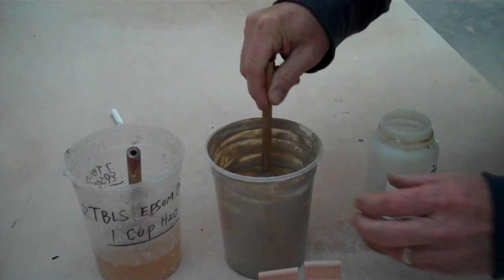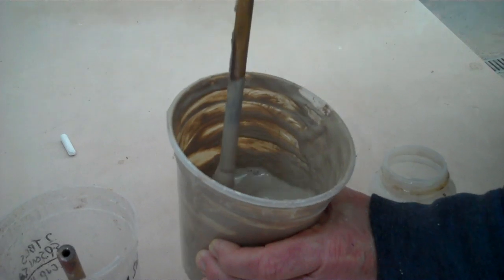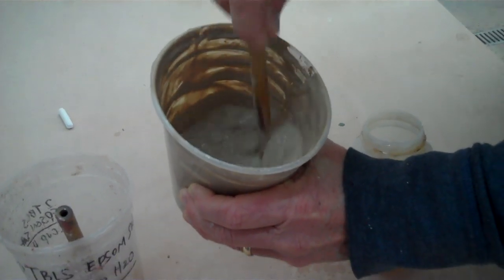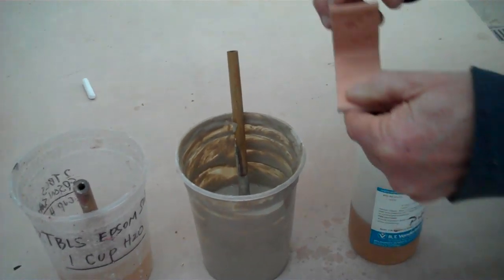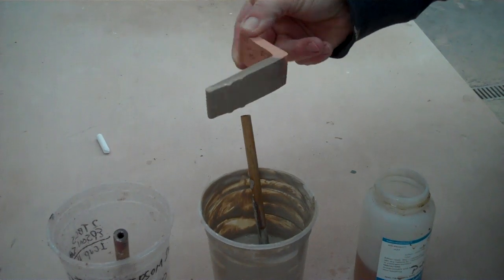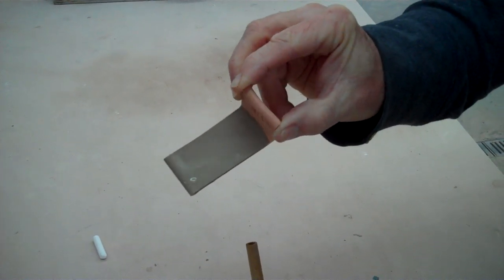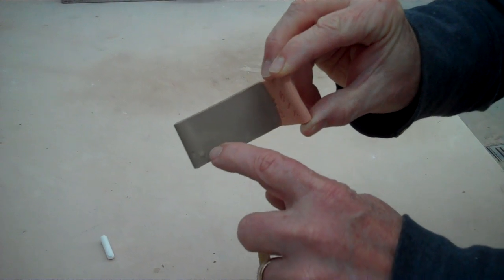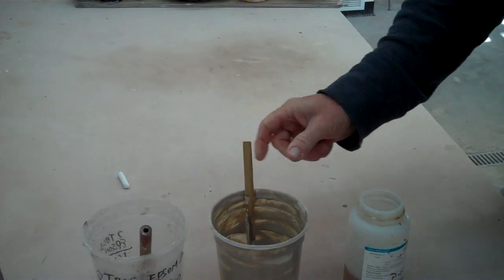Okay, look at how that was. That was really about two small drops and it's totally deflocculated. You can see it swirling in there, marbling on the surface. And now when I dip my tile, look how watery it is and how it has frozen drips like that. That's an indicator of deflocculation.